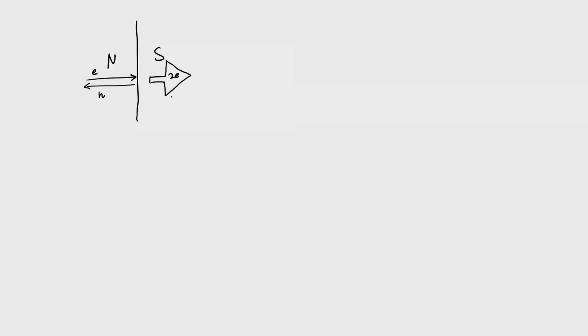Okay. So, this is that Cooper pair, and since Cooper pairs can travel inside a superconductor, it would travel, and this electron gets annihilated and there is a hole. So, this electron has spin up and the hole has spin down, and basically this can give rise to low energy tunneling current. So, at very low energy you do not need to actually cross the gap, you still can have tunneling current even at 0 bias, that is very low energies. So, this is known as Andreev reflection.